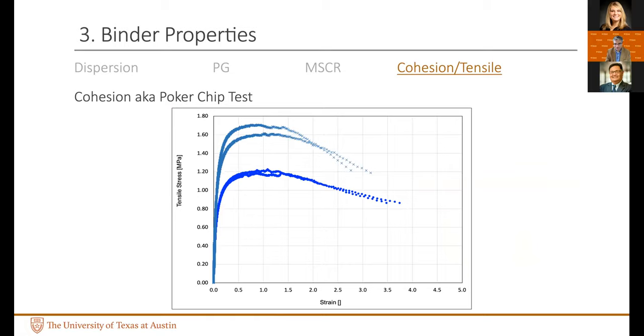And what you see here are the control and the plastic modified asphalt binder. Again, just as with the mixture results, you see the same thing. With plastics, you see an increase in tensile strength. This is what you saw in two different mixture tests earlier, and a little bit of loss in ductility, which is what you're seeing here. So this is consistent with the previous test.